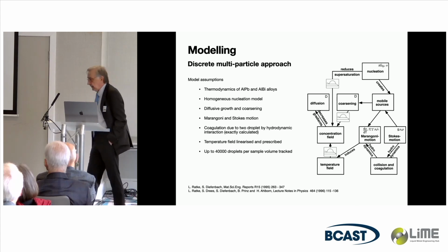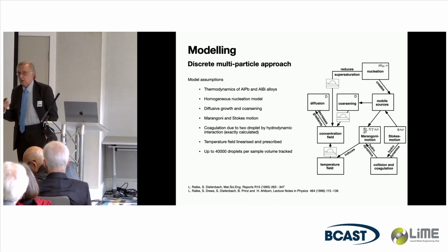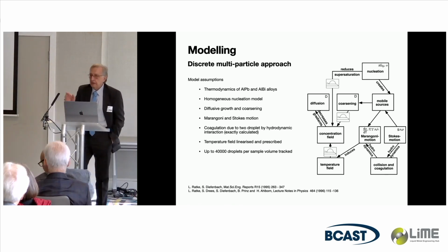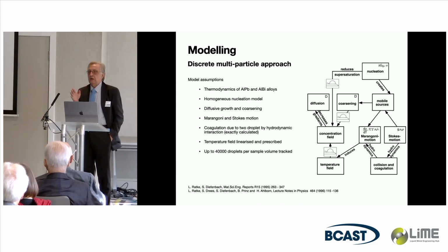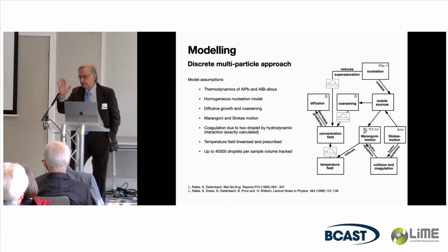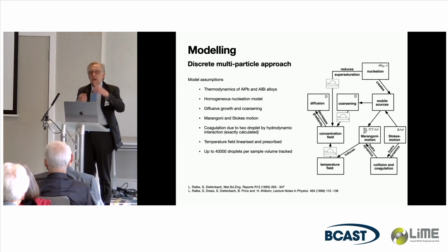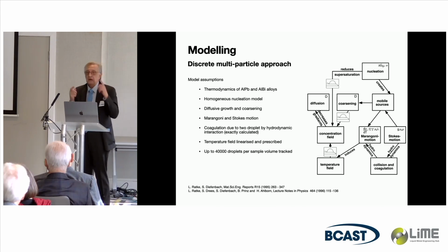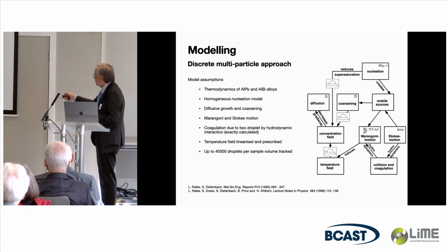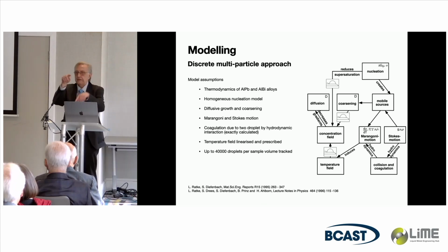To take that into account, you have to have a good model of how to describe coagulation. And let me make a simple example. If you drive in winter through falling snow, you will note that not every snowflake hits the windscreen. A lot of them just pass by. There are enough hitting the windscreen, but a lot flow by. And this is due to hydrodynamic or, in the case of snowflakes, aerodynamic interactions. So if you would like to do this correctly, you have to calculate the flow around the droplets, either doing Stokes motion or Marangoni motion.